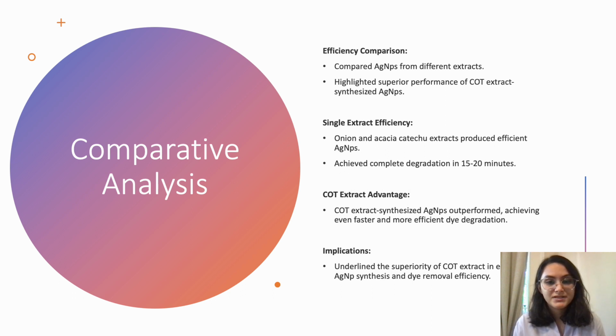Now let's explore the efficiency comparison of silver nanoparticles synthesized from different extracts and their implications. In this study, researchers compared silver nanoparticles synthesized from various plant extracts. Notably, they highlighted the superior performance of silver nanoparticles synthesized with the combined COT extract. It is worth mentioning that silver nanoparticles synthesized from single extracts such as onion and acacia catechu were already efficient in dye degradation. They achieved complete degradation in relatively short times, which was 15 to 20 minutes. However, the COT extract synthesized silver nanoparticles outperformed the others, achieving even faster and more efficient dye degradation. These findings underscore the superiority of the combined COT extract in enhancing silver nanoparticle synthesis and also significantly improving dye removal efficiency.